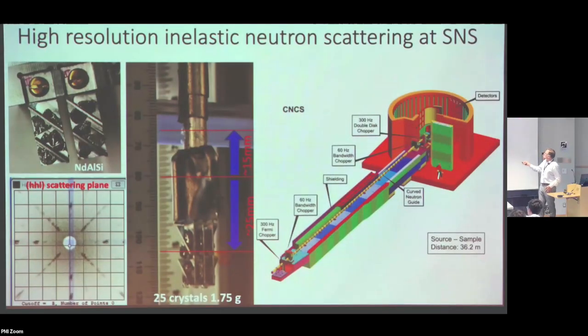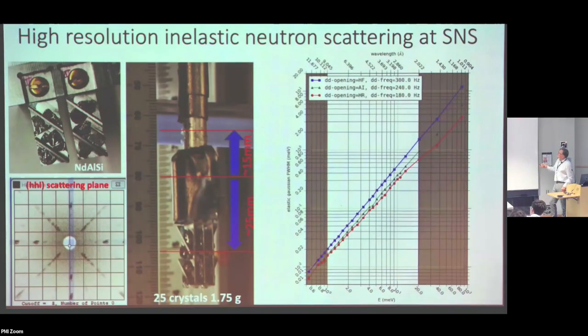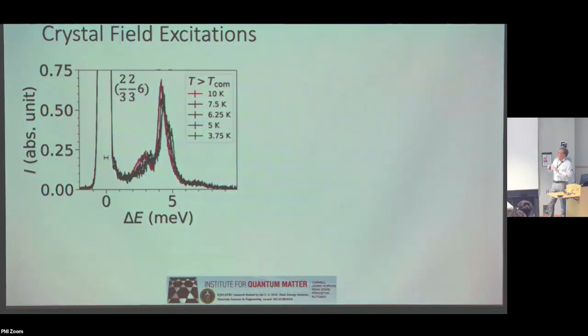This is the machine, that's the person, so these are really room-sized instruments, completely covered with detectors 36 meters from the source. And that's the resolution. There are several different configurations, but we can get all the way down to 20 microelectron volt resolution by choosing the incident energy and also some configuration of choppers that are part of the instrument. And so then this is what you see experimentally. This is basically crystal field excitations, which we also talked about yesterday. And it's neodymium again, which was actually what we showed yesterday. So it's a lot of stuff that is very similar, but then some things that are different.